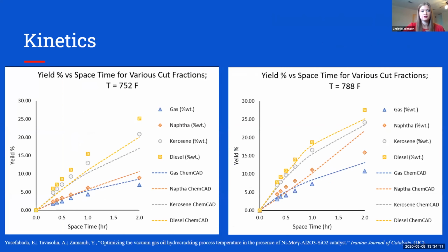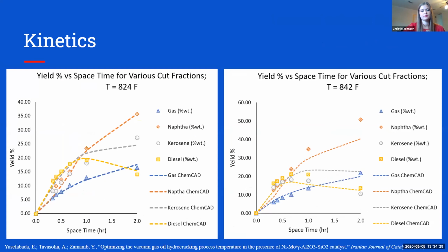And this is just to show you sort of the results of that kinetic validation. So you can see that the trends do track as the temperature changes and as the diesel and kerosene start to curve down in the literature, they start to curve down in our simulation as well, showing that they're being cracked into lighter products. And that continues at higher temperatures. They continue to crack into more of those naphtha and gas products.